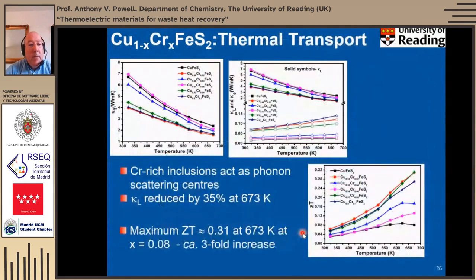However, these inclusions seem to have a very beneficial effect on thermal transport because they act as phonon scattering centers, and they reduce the lattice contribution of the thermal conductivity. So that's this set of curves here. This is the lattice contribution, this is the electronic contribution, this is the total thermal conductivity. It reduces the lattice contribution to thermal conductivity by about 35% at 673 Kelvin. And that actually allows us to increase our figure of merit by a factor of almost 3 compared to the end member copper iron sulfide. And we can get up to, at the moment, 0.31 at 673 Kelvin.